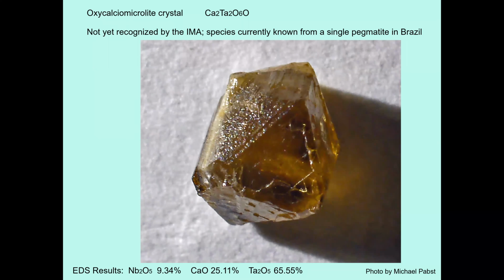This is the third microlite group species tentatively identified by EDS testing. Note the unusual greenish yellow color of this perfect crystal and its simple chemical composition: niobium, calcium, and tantalum. This was identified by Tony Nikisher of Excalibur Mineral. He and I both are very confident that this is Oxycalcio-microlite, and at the time this was analyzed, it still had not yet been officially recognized by the IMA.